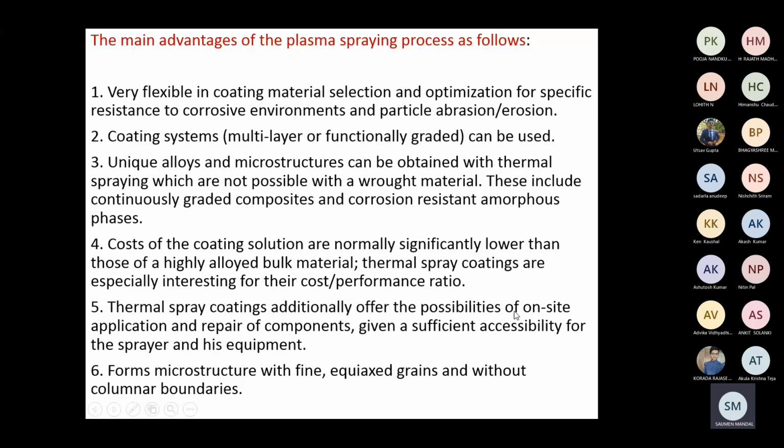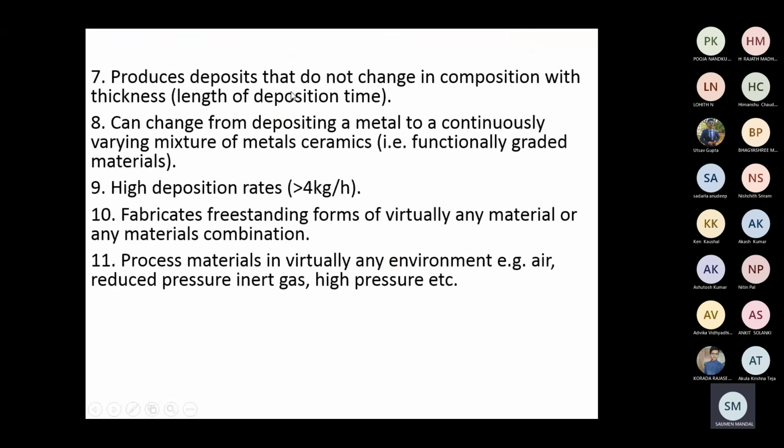It additionally offers the possibility of on-site application and repair of components. On-site means you need not do that part in another area, given sufficient accessibility for the sprayer and its equipment. So this coating we can do on site, and for repair purposes. It forms a microstructure with fine equiaxed grains without columnar boundary. That's why you get that hard coating, and it produces deposits that do not change in composition with thickness. That is a unique advantage.